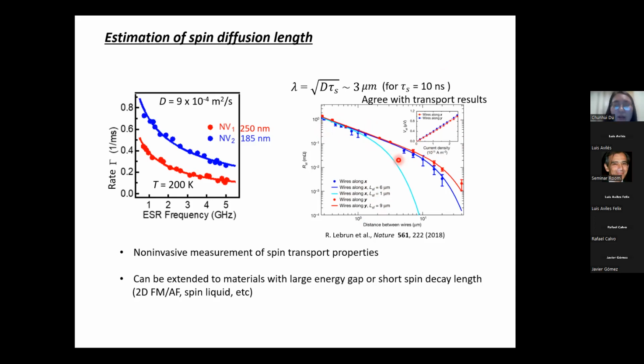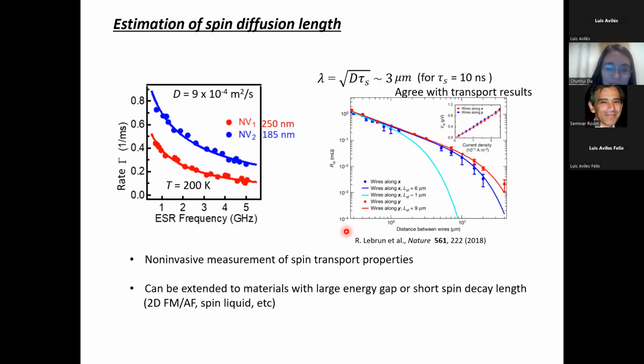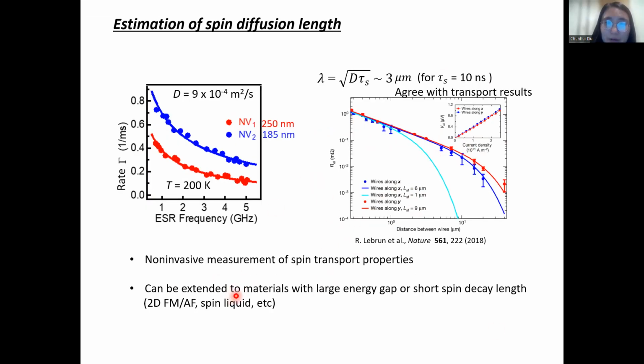And we also want to highlight that in this case, we measure the spin relaxation rate of the NV center in thermal equilibrium conditions. So it's a non-invasive measurement to study the spin transport properties. And also, because our measurement is very general, we don't need to pattern the electrode using nanofabrication techniques. So this allows us to study material systems with relatively short spin decay lengths and with large energy gap, for instance, two-dimensional ferromagnetic and antiferromagnetic materials, as well as spin liquids.